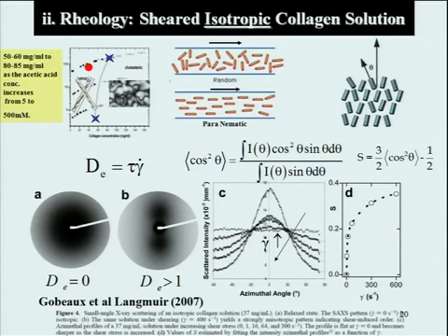In the isotropic phase, we make a paranematic phase by shearing the system in the isotropic phase. And these are SAXS experiments, no flow, you have isotropy, flow, you have anisotropy, this is the scatter intensity, and out of this you plug into this formula and you get the scalar order parameter that goes from 0 as a function of shear rate and goes all the way up and eventually saturates around 600 reciprocal seconds. The value of the scalar order parameter is around 0.4.